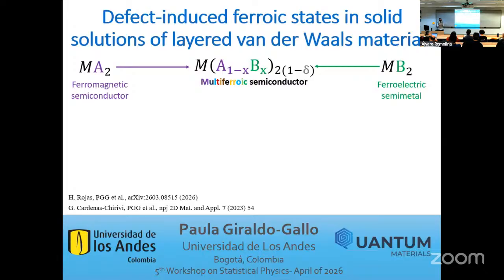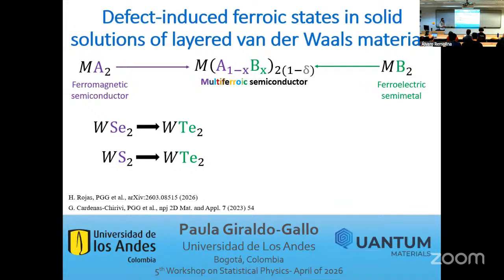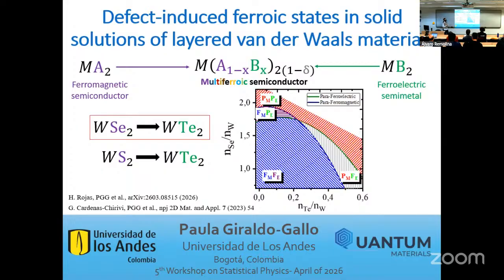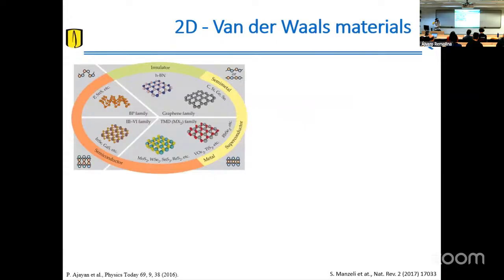Through this, we have observed that we can promote a multiferroic state, which is the simultaneous presence of different ferroic states in these materials. And in the beautiful work of my students in the group, we have been focusing on two main systems, the mixture of tungsten diselenide and tungsten disulfide with tungsten ditelluride. This generates these beautiful phase diagrams, which show the behavior of the different ferroic states. Depending on the relative composition of selenium, tellurium, and the amount of defects in the material, we can have multiferroicity in a big portion of the phase diagram, or just a paraelectric material with ferromagnetism, which will be this one, or vice versa. We can have all the mixtures of these different ferroic states. So I'm going to show you a little bit about how we get there.